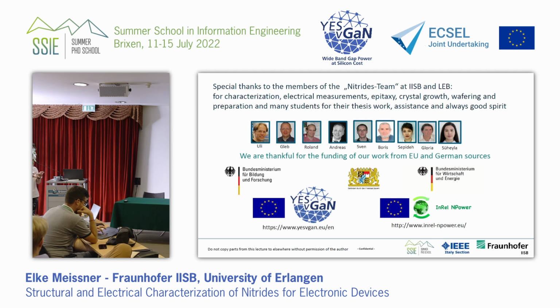Because later you go from a 3D nucleation, which is what you're doing in these little islands in the nucleation layer, and then you want to achieve a layer-by-layer 2D growth. There is a transition which is a function of all the parameters that I said, including the temperature regime where you grow the nucleation. Okay, thank you. And these need to be optimized.